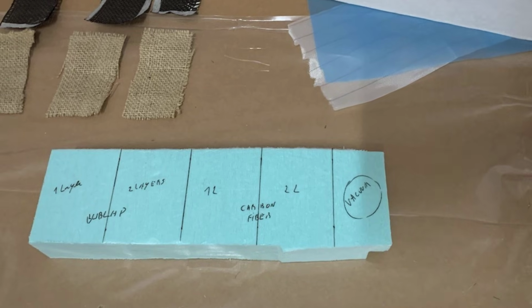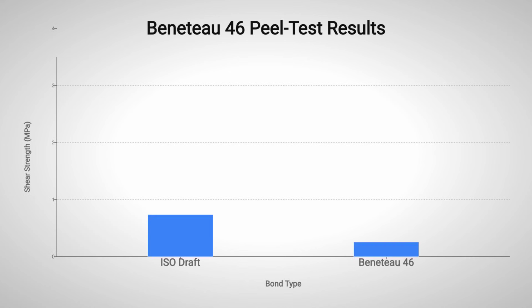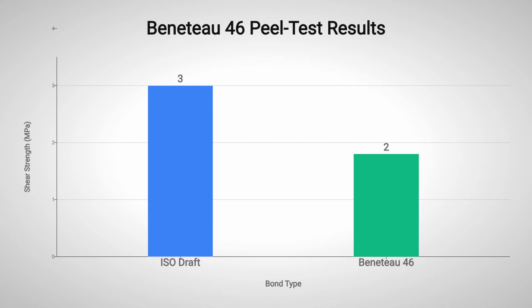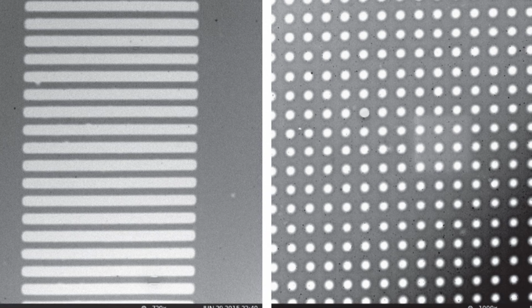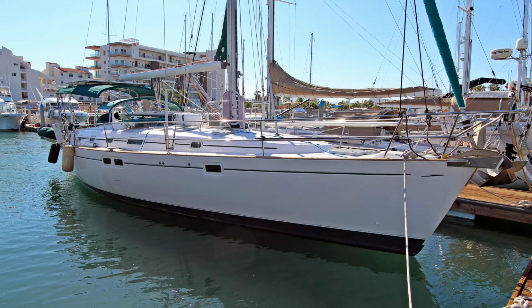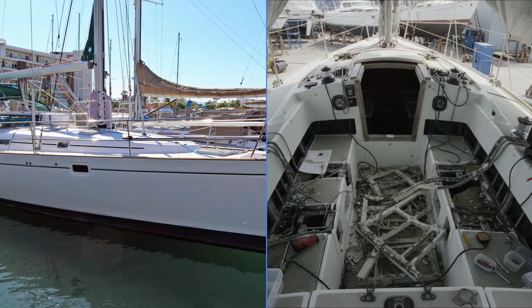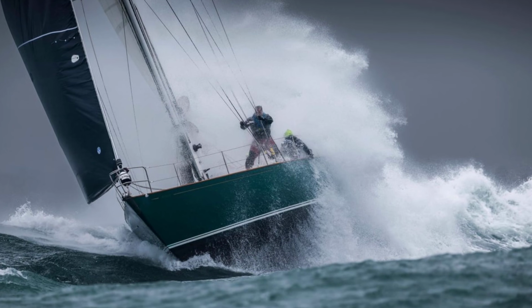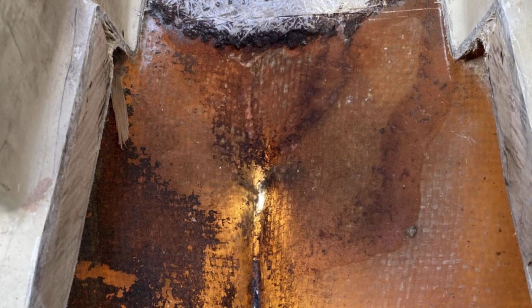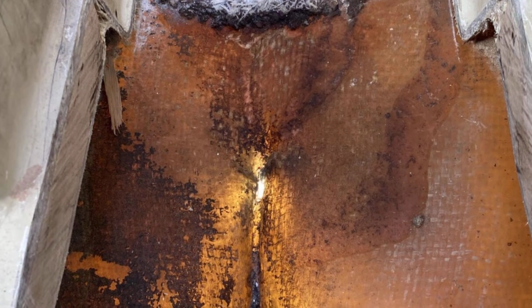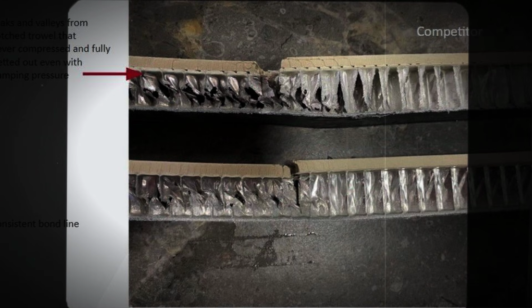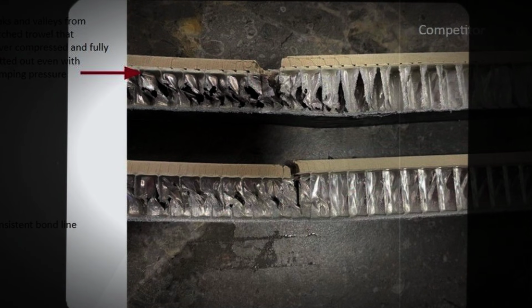Peel coupon samples from the failed area tell the rest. The lab certificate reads 1.8 megapascals, far below the 3 megapascals standard now under ISO review. The secondary bond, a thin film of methacrylate adhesive, depended on surface roughness and luck to keep the grid attached to the cured polyester hull. Under the strain of a gale, it failed, and the grid, meant to be the boat's backbone, became just another loose component.